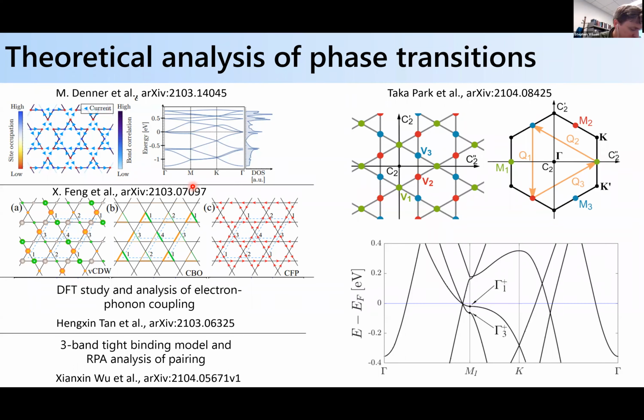Okay, so they're somewhat linked questions. I'll tackle the second one first. You don't see the distortion in the powders simply because the superlattice peaks, as probed by synchrotron X-ray scattering, are too weak. They're four to five orders of magnitude weaker than the primary peaks, and with powder averaging you just miss them. So you need single crystal diffraction, even at a synchrotron, to see it.